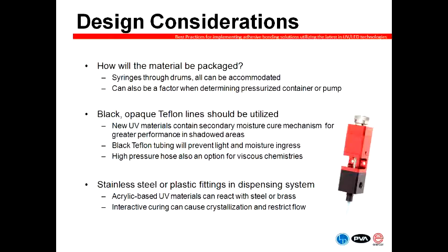Typically, we're using stainless steel or plastic fittings in the dispensing system. Acrylic-based UV materials at times can react with steel or brass units. Those are considerations that should be taken when designing a UV dispensing process. And during that curing phase, any type of crystallization due to inappropriate fittings or fluid delivery components would obviously restrict the flow of the material and subsequently clog a valve or a dispensing system.